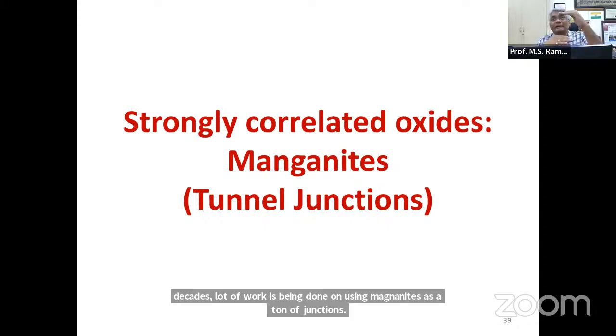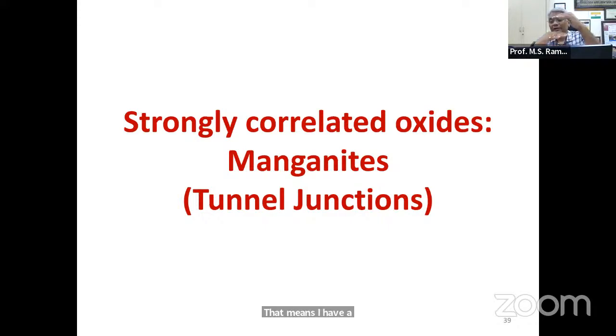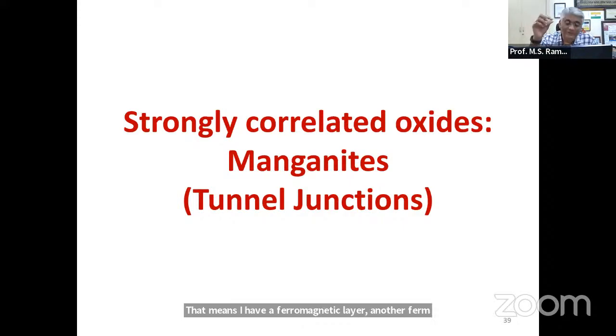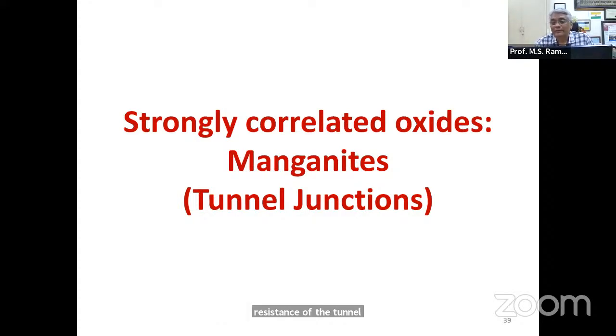If you now look at strongly correlated oxides, for the last 4 decades, a lot of work is being done on using manganites as tunnel junctions. That means I have a ferromagnetic layer, another ferromagnetic layer separated by an extremely thin nanoscopic level of insulating barrier. And then I can control the resistance of the tunnel junction by controlling the width of the tunnel barrier.